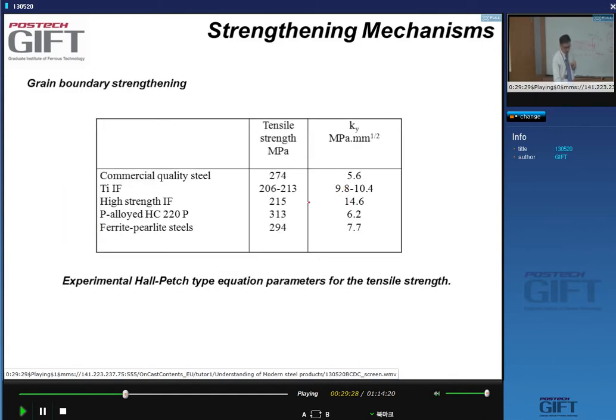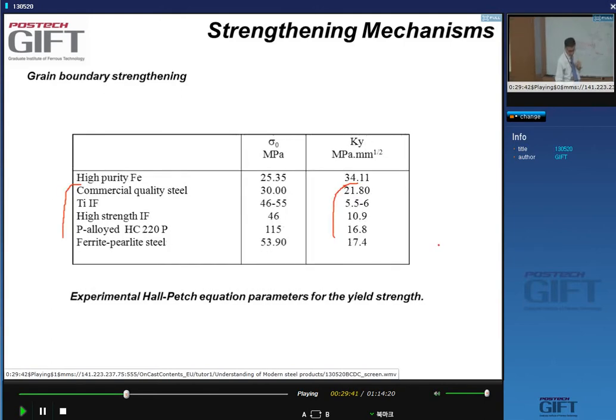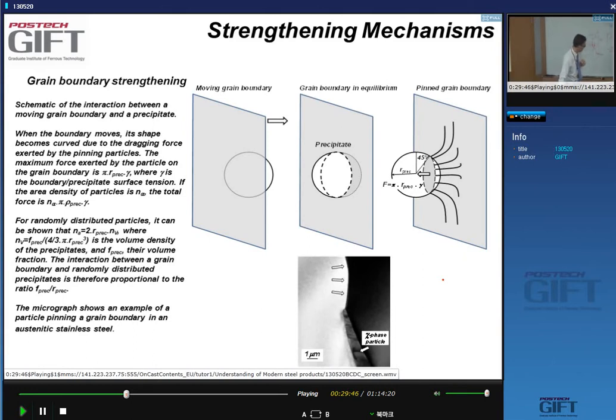The Hall-Petch equation holds not only for the yield strength, but also for the tensile strength. We'll come back to what the implication is of this difference. But the fact that you can get quite a lot of strengthening just by reducing the grain size is, of course, very interesting from a technological point of view, because the grain size is controlled by processing. And so we will try to get in steels an optimal grain size. And the way this is done is by adding precipitates to our steels.